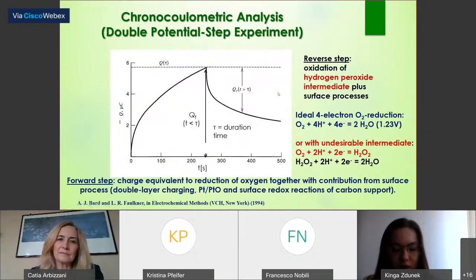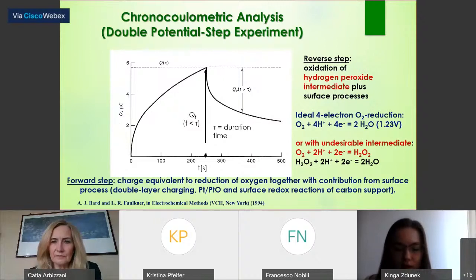On this slide we can see typical double potential step chronocoulometry. This method measures the dependence of the charge on the duration of the electrode process at a constant potential. The sign is negative because reduction is the forward step. Here we observe the charge equivalent to the reduction of oxygen together with the surface process, and next we observe the reverse step, and this is oxidation of hydrogen peroxide with a surface process.